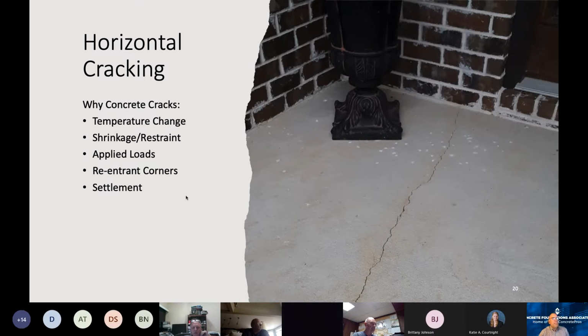And so that's a classic example right there of horizontal cracking coming from shrinkage, the volume change. And I'll be willing to bet anything, in this particular case, the contractor used a high water mixture, a high water cementitious ratio. They were probably either wheelbarrowing it in or they might have been direct shooting and wanted to make sure it flowed in there well. And it probably didn't have a high constituent of aggregate. And lo and behold, as that concrete tried to dimensionally change, it's anchored at the left side there against the brick wall. It's anchored on the opposite side. We're looking in on the short side, and it just tore itself apart.